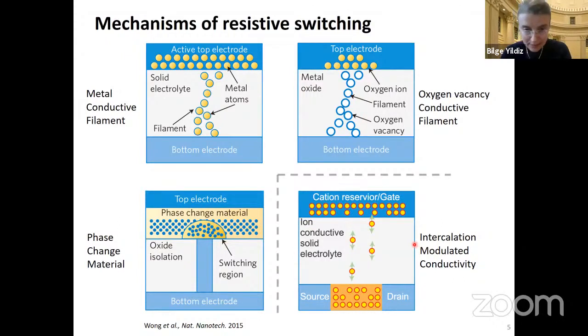more interesting recently, that has come to our attention more recently, is via the intercalation of ions into a switching material. So this orange layer would be an insulating material, and we have a cation reservoir, such as lithium in your lithium-ion batteries. And just like in your battery, you can move those lithiums into this insulating layer and change the conductivity of this layer. And I will share with you in the rest of the talk our work on such cation intercalation-based inorganic synapses, as well as those based on oxygen vacancy conducting filaments.